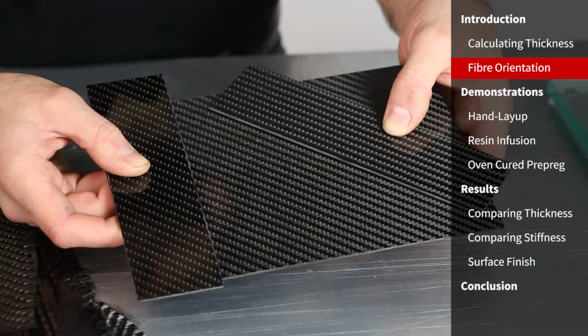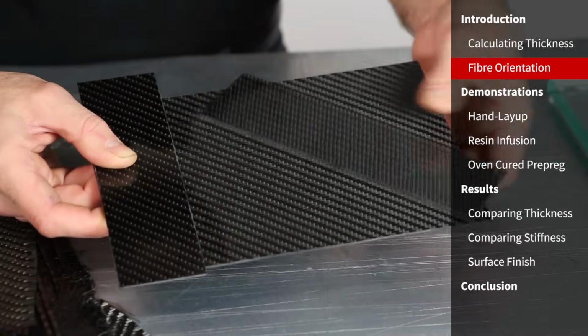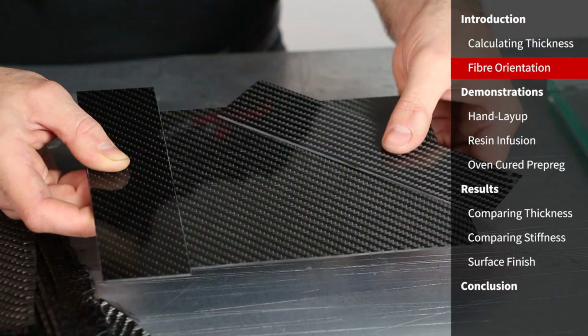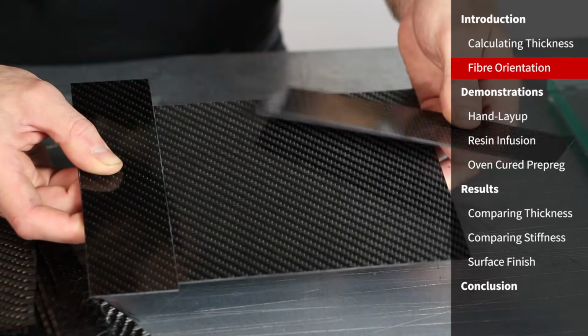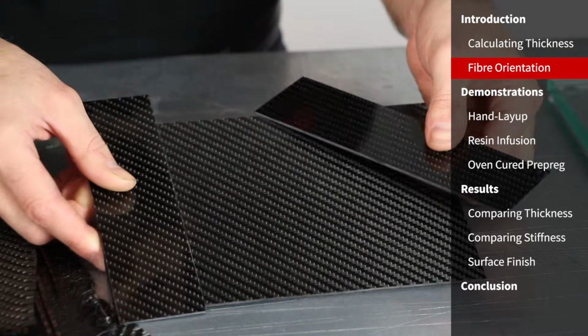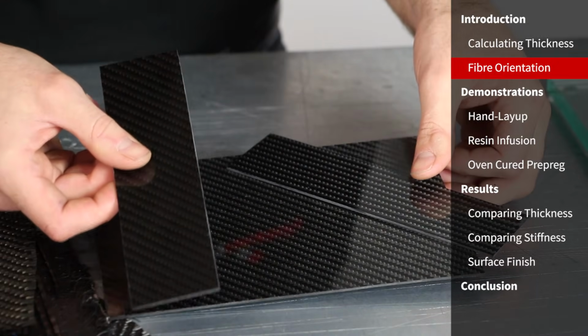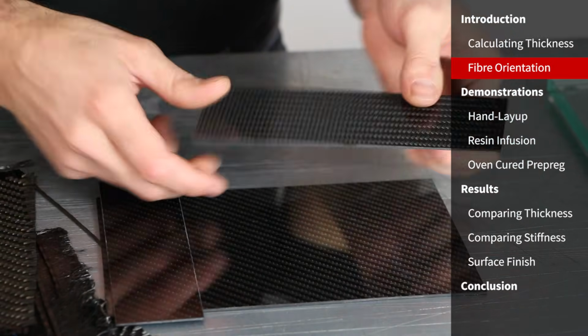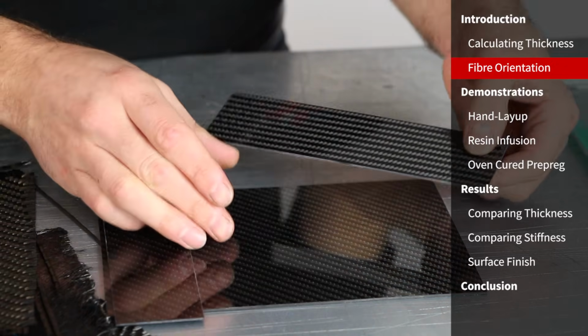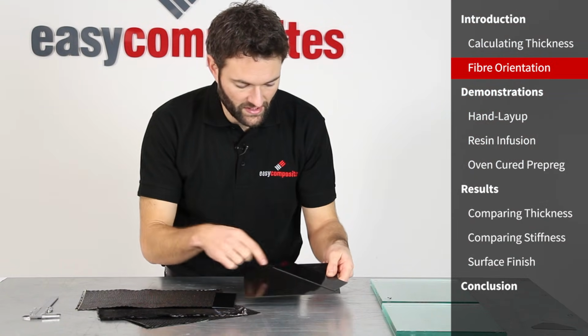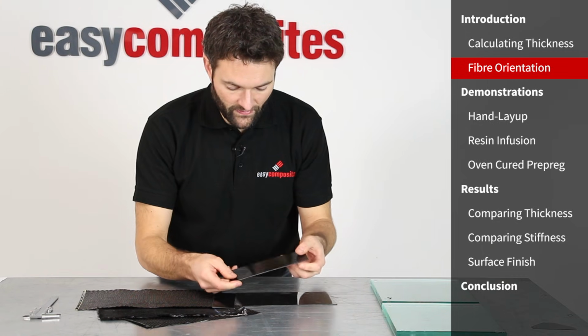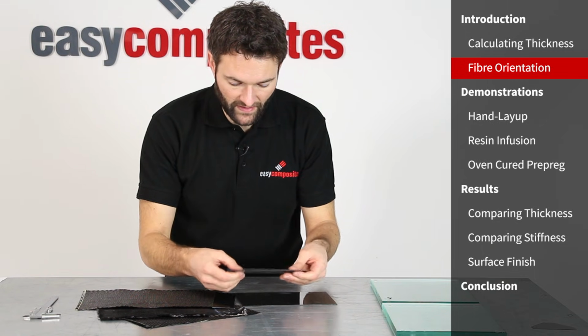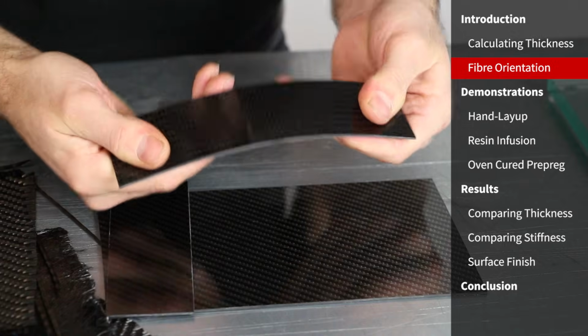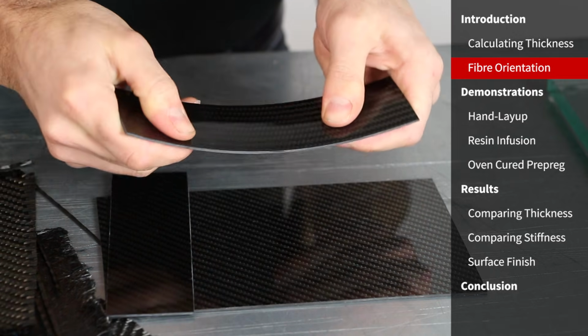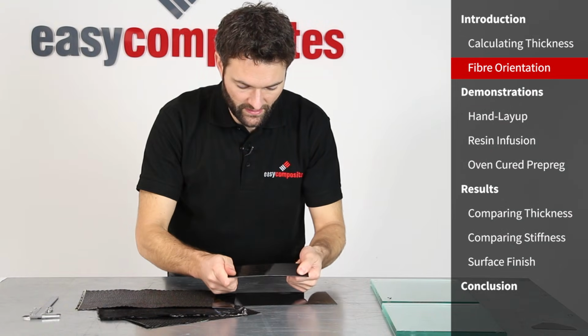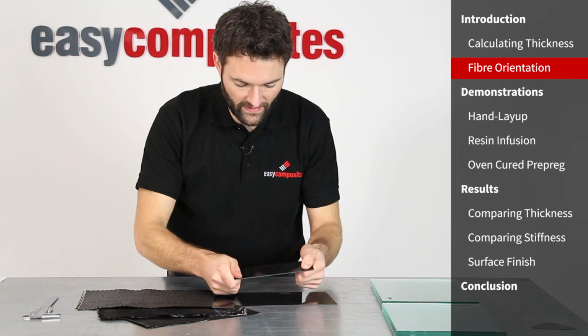So this is an example that we use on our training course. We've got these two test pieces or samples that have been cut from exactly the same carbon fibre sheet. This one's been cut at this angle and this one's been cut at 45 degrees, so you can see the weave pattern matching the sheet that it was cut from. So if we take this section that was cut at 45 degrees, I can really bend this sheet very, very easily. If we try and twist it torsionally, crikey, very, very strong in that direction.